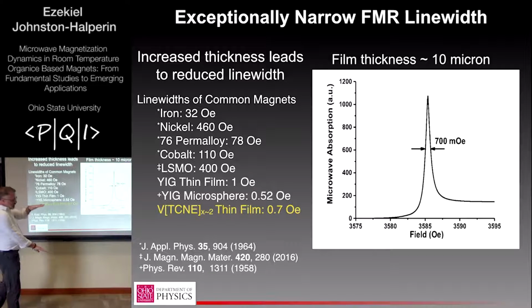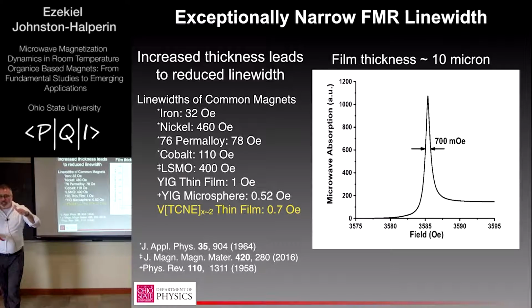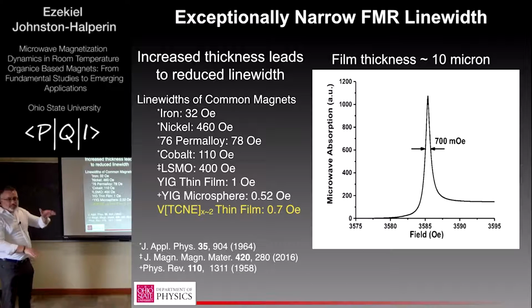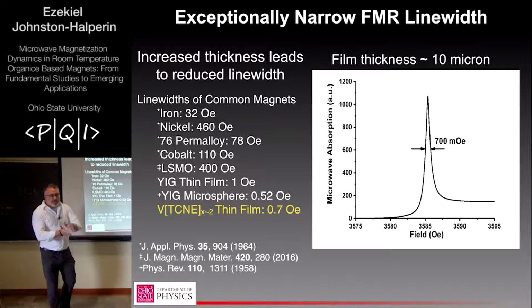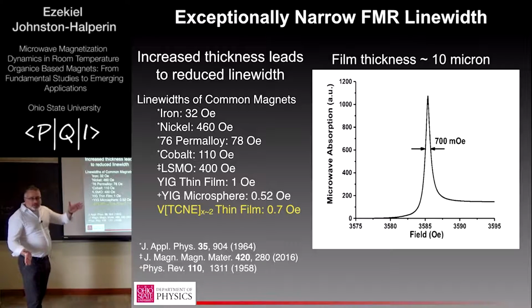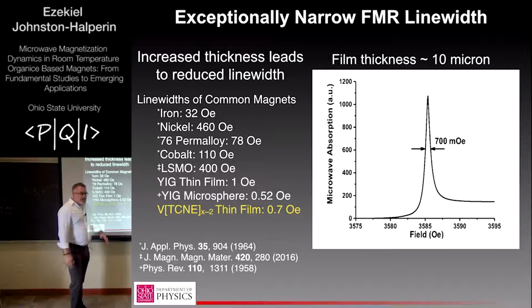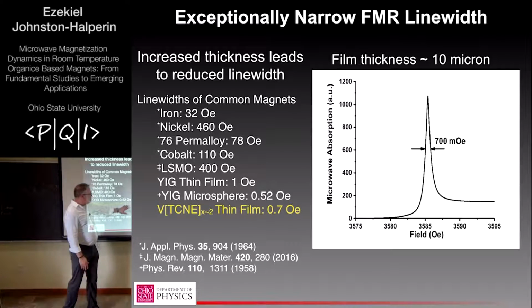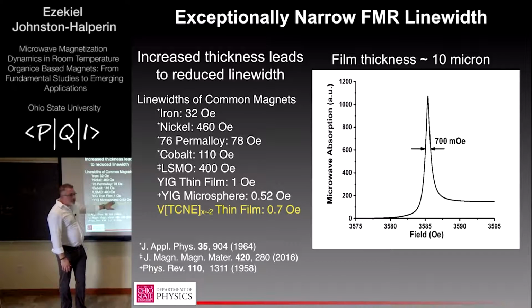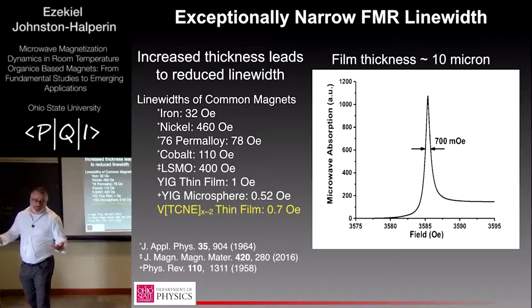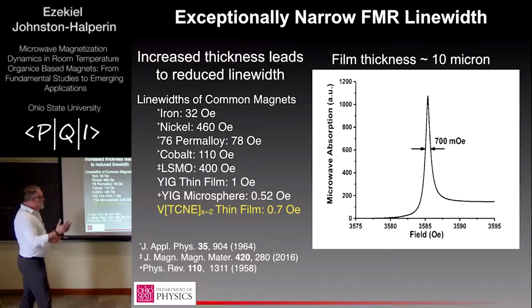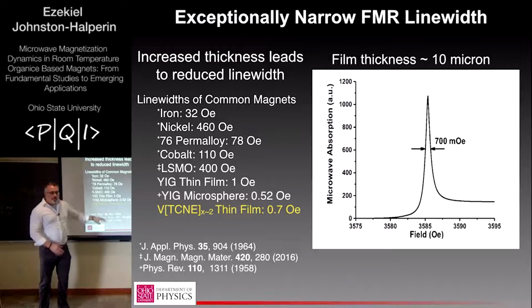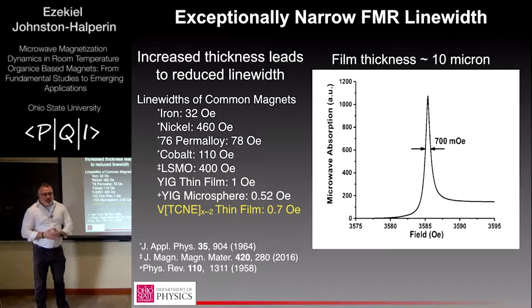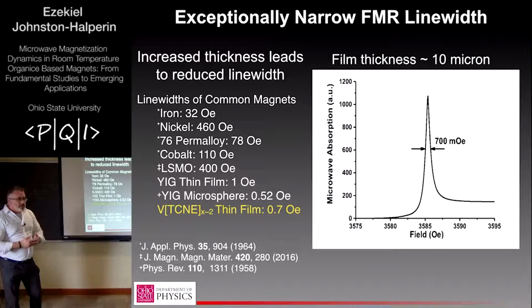And the reason the thickness helps you here is there's magnon-magnon scattering that happens at interfaces. So it's generically true of all these materials that as you make them thinner, the line widths get broader. So having a bulk material can help your line width. So now we've taken that line width that was a little larger than a Gauss for the thinner films. For these thicker films, it's now getting close to the polished YIG microsphere, which is basically the gold standard for magnetic resonance. So this, coming back to Jeremy's very nice introduction, this is sort of why I think we have reason to claim that these materials are competitive with really the best magnetic materials out there.